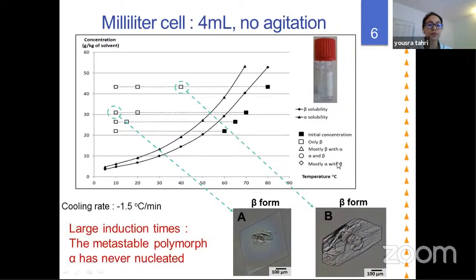So to sum up, in general we had large induction times for these experiments, but we never could observe the metastable polymorph alpha, even at low temperatures.